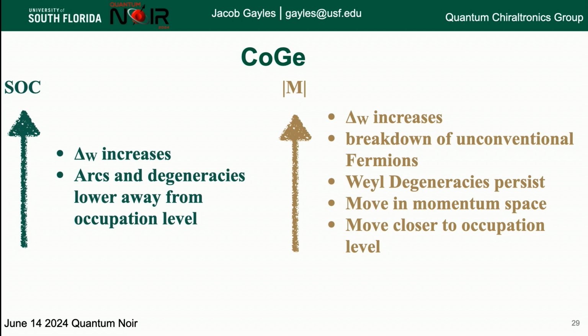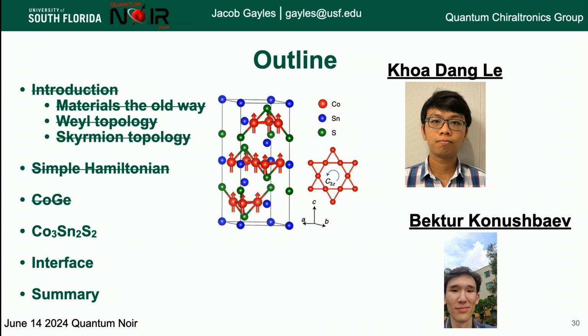However, when we start adding magnetism, we can also change the distance of the Weyl points, and then we also break down those unconventional fermions, which is spin 1 and spin 3/2, and we can also move them in momentum space. And they move back up closer to the Fermi energy, which is a good thing. Good. So we take a break from the cobalt germanium, this chiral compound, and come to what's called cobalt tin, Co3Sn2S2, which is this Kagome material, which looks very similar to graphene, but it has a hexagon in the middle and stars, triangles on the outside.